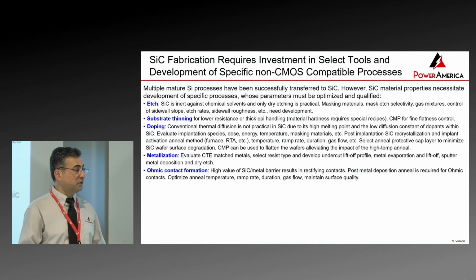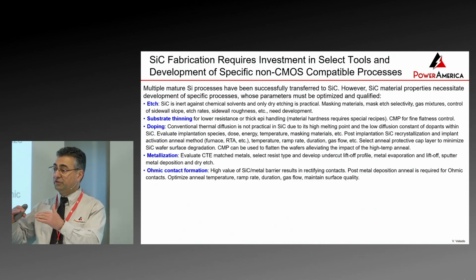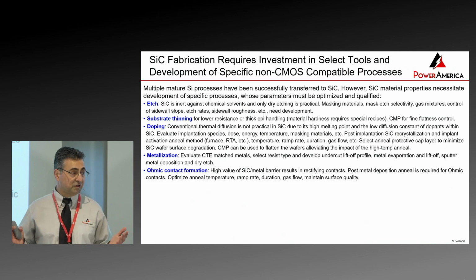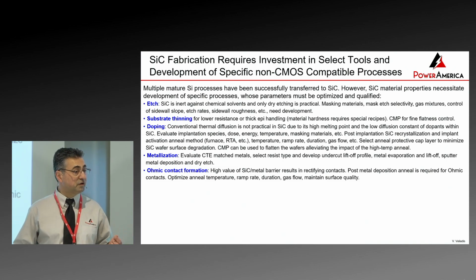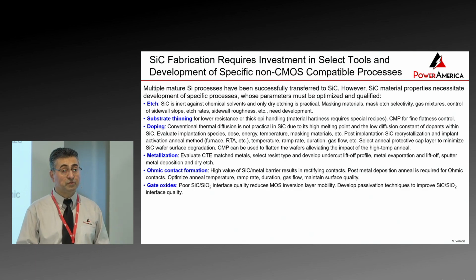Ohmic contact formation: because of the high band gap, if you put metal on silicon carbide, you're going to get a Schottky. So the question is, how do you get a low resistivity ohmic contact in silicon carbide? Another process that needs to be developed.